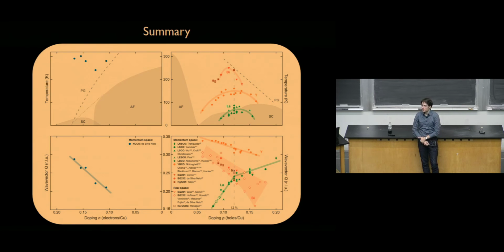So by tracking the amplitude as a function of a bunch of different experimental parameters, you can look at how that particular electronic order behaves in comparison to other electronic phases that you might have studied with transport or other tools. Are these really small amplitude oscillations in charge density, or how large are they? It's hard to tell because we don't really probe the charge directly. There's no technique that can probe the charge directly, right? So that's not an observable for our method. We can infer that by some special methods, like by comparing that to how strong the scattering is for some Bragg reflections, for instance, that have a very well-known structure factor. But it's still very hard.